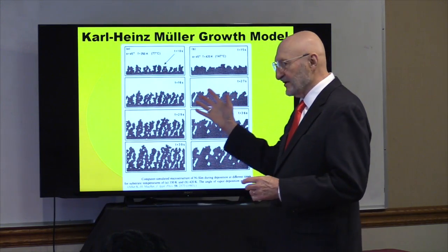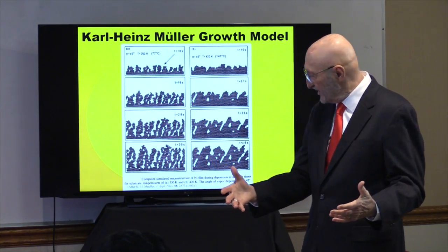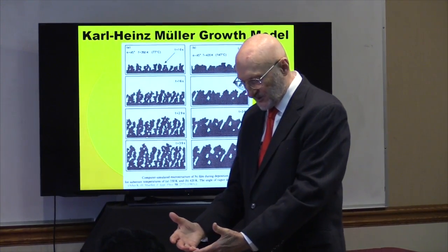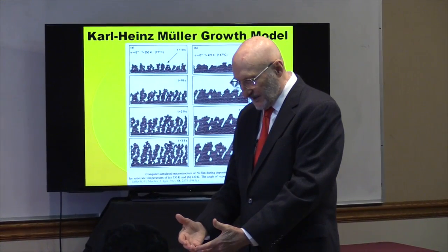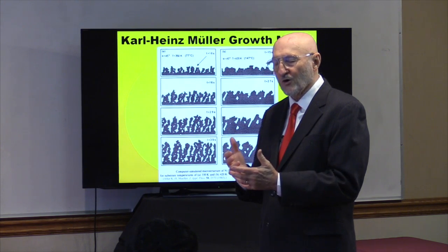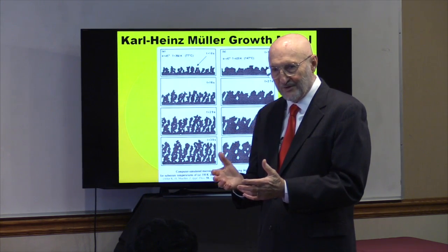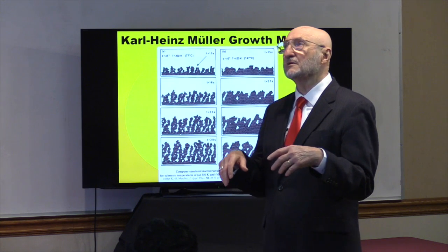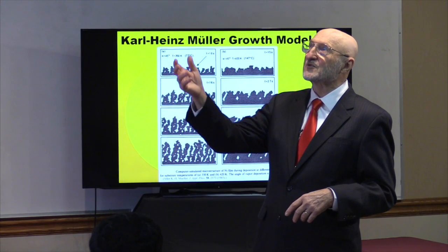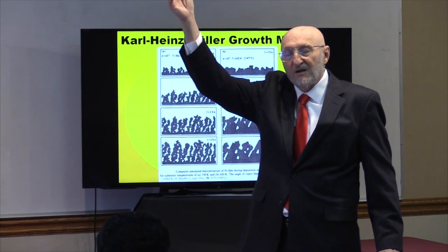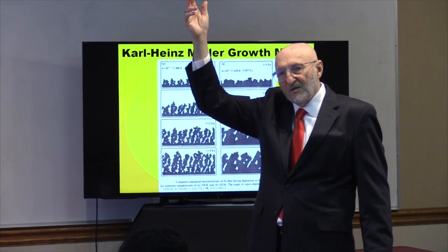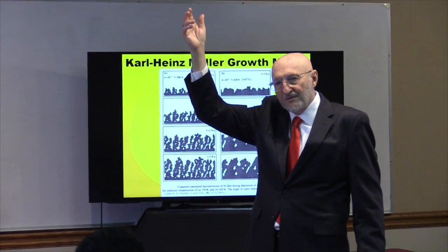As I describe it, when a molecule evaporates, an atom evaporates, we'll say magnesium fluoride, the energy it has as it leaves that surface is on the order of 1/10 of an electron volt. That's like it just goes, okay, if you insist. And it meanders up to the substrate, and it bumps its head on the substrate and sticks. And it can't move anymore, it's lost all its energy.